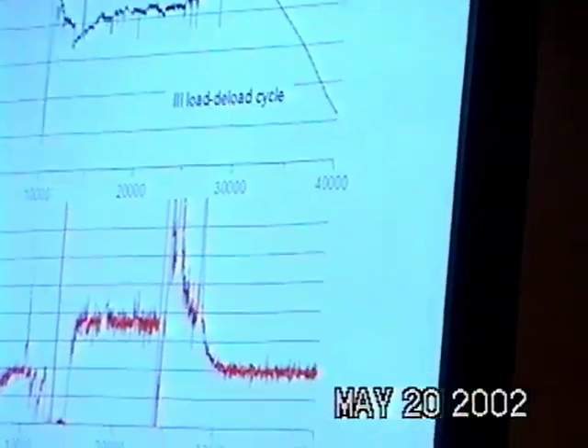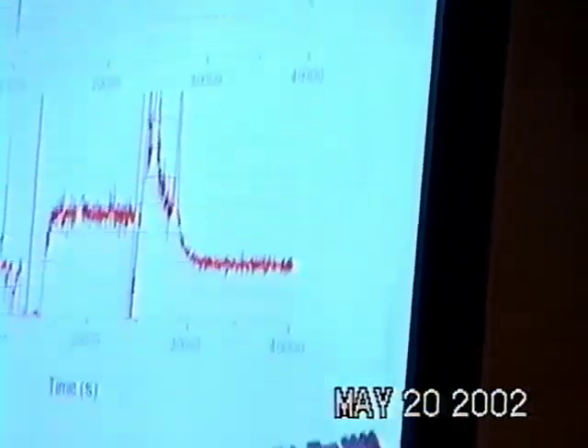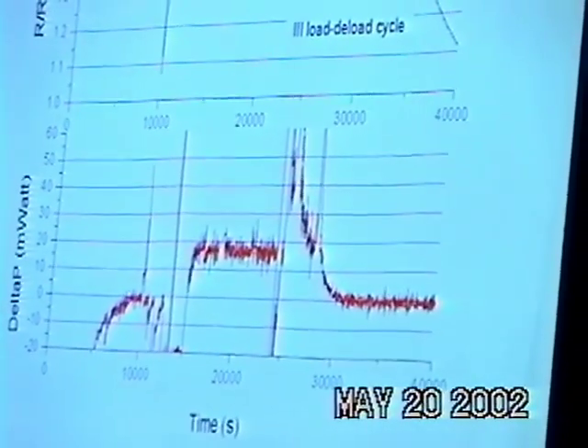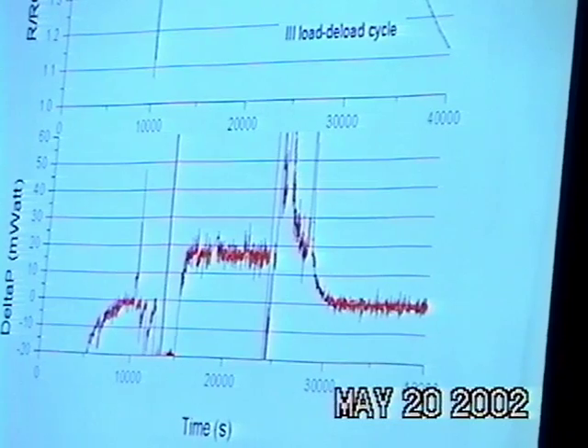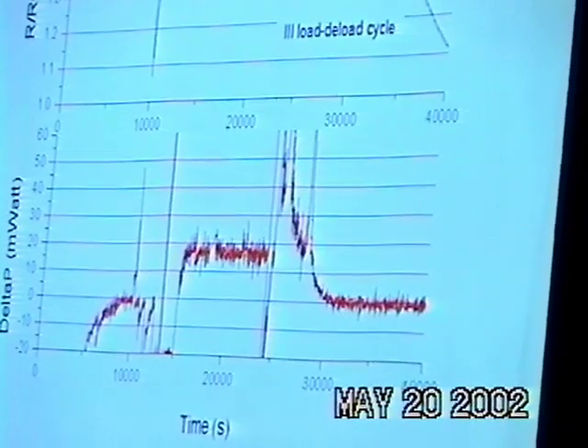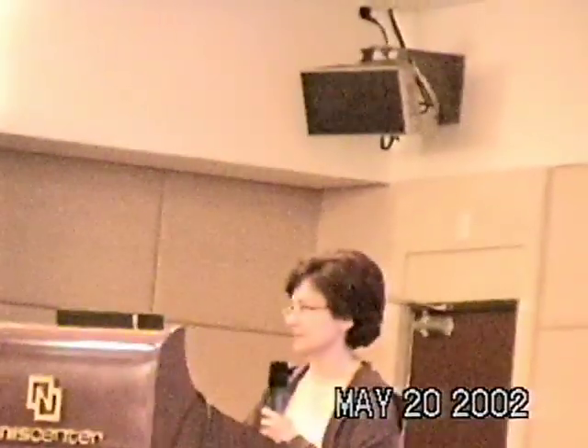We tested different samples on different substrates in order to improve the calorimetry. Calorimetry is obtained by putting in very good thermal contact the substrate of the deposition with the Peltier element, a commercial Peltier element. This way we measure the voltage across the Peltier element and avoid losing heat in heating the water of the cell, and avoid losing heat through the film boiling effect. It's a quite good calorimetry, but it's not enough, as you will see in a moment.